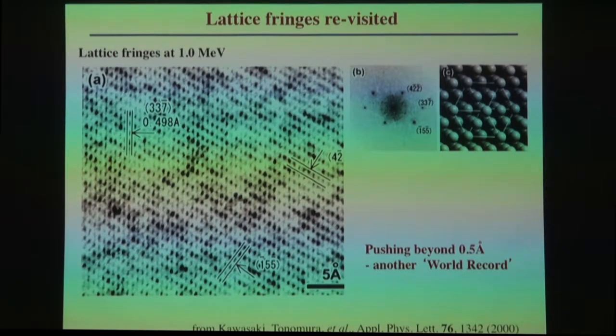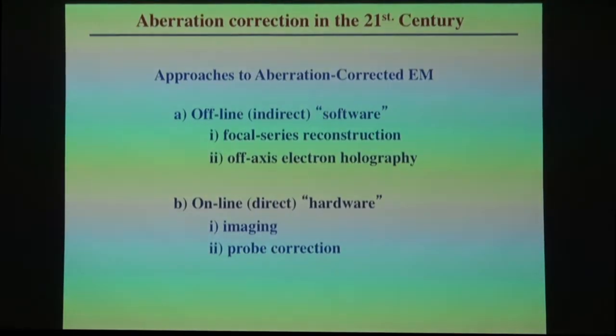And here we are with another image from Tonomura's laboratory. Lattice fringes coming back again at 1 million volts. I think you would all have to agree, you can all see these vertical fringes. These vertical fringes have a spacing of 0.498 angstroms. I don't think anyone is going to argue with the ability to see these vertical fringes separated by 0.498 angstroms. But none of you, not me, and I've looked at a lot of micrographs over the years, can tell you where the gold atoms are in this sample. This is an indication that the microscope was very stable, the environment was very stable, no magnetic vibrations, no interference coming from anywhere. So we're moving into the 21st century